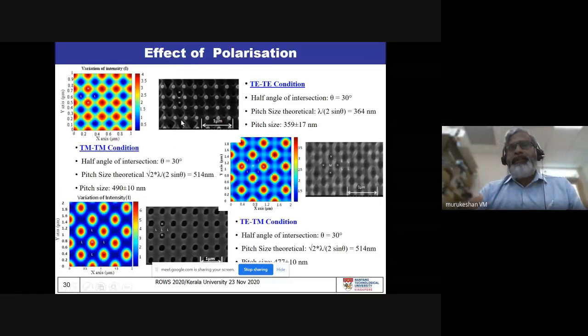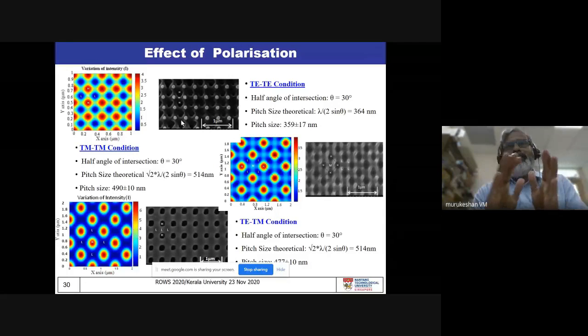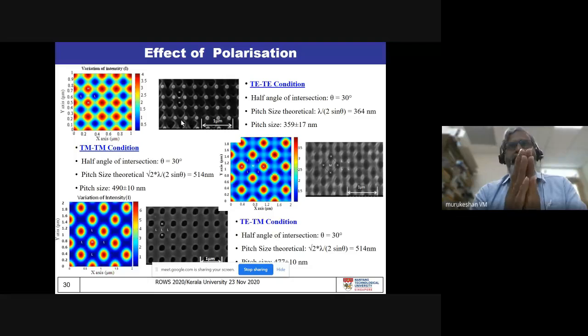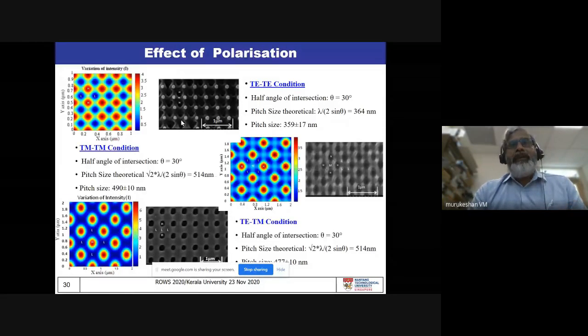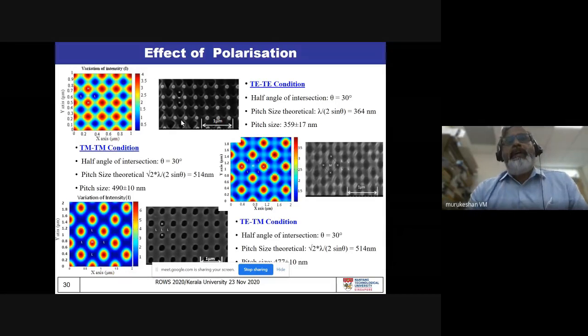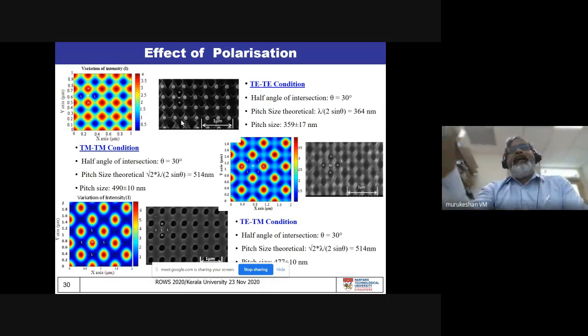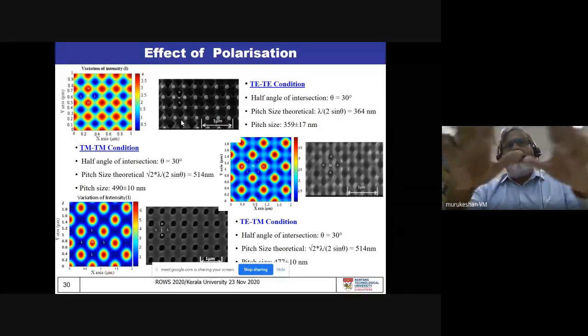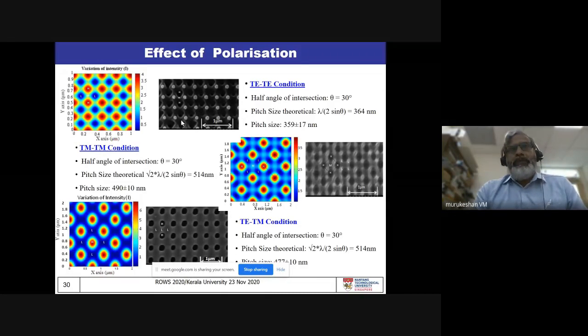And I didn't show you that. I would also like to emphasize that with Professor Joby Joseph from IIT Delhi, we had done a very interesting work. We not only changed the polarization, we were changing the intensity ratio between the interfering beams as well as the phase of the beams, and we were able to fabricate or come up with features which are equivalent to the crystal lattice structures, as well as many different interesting structures we were able to make.